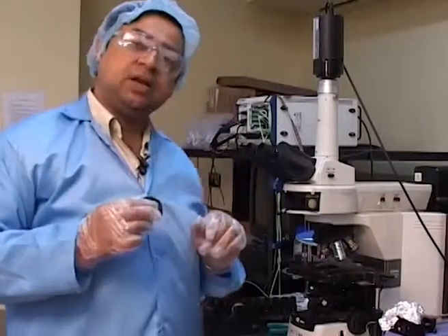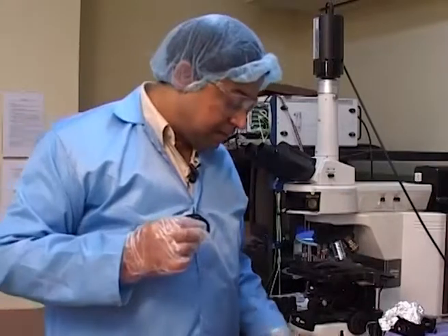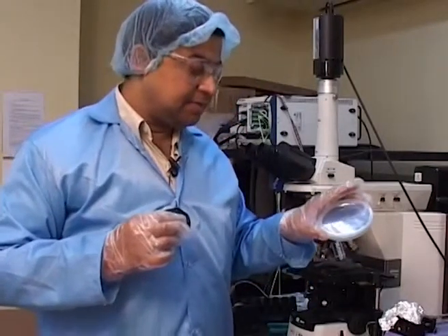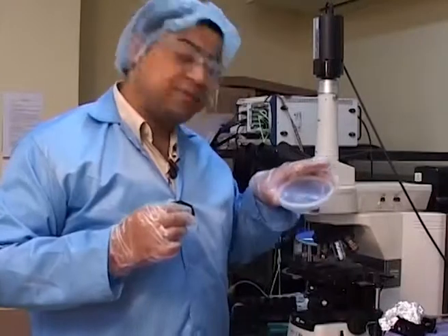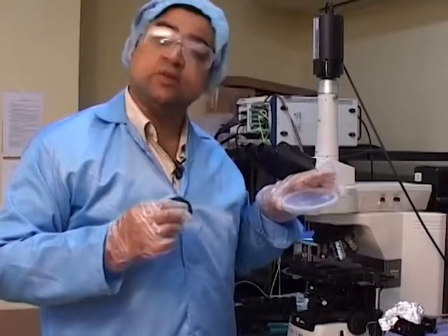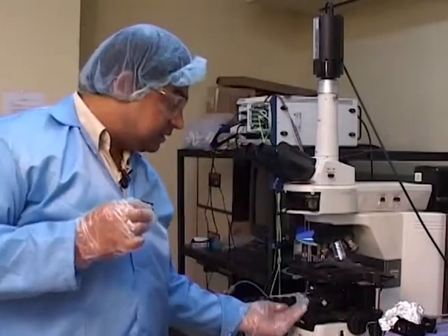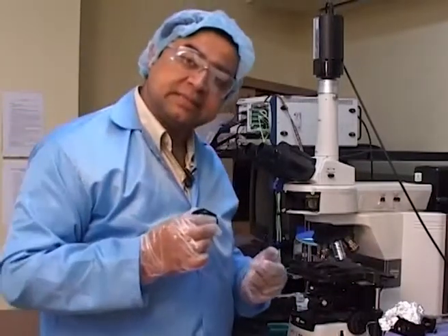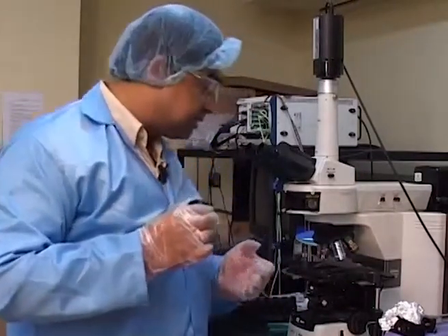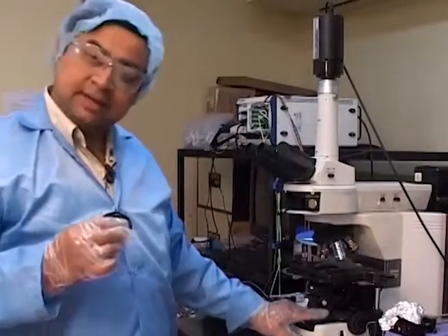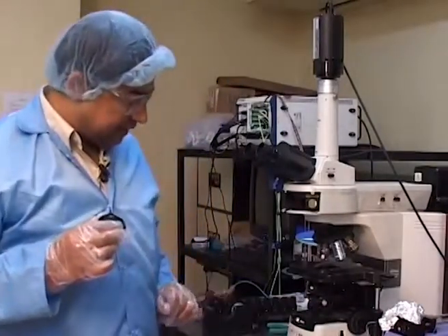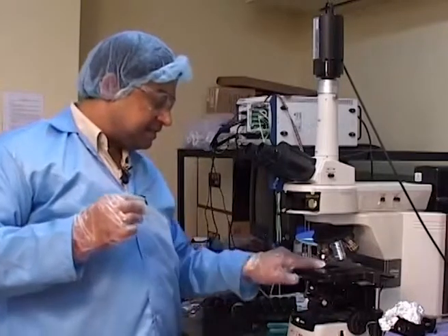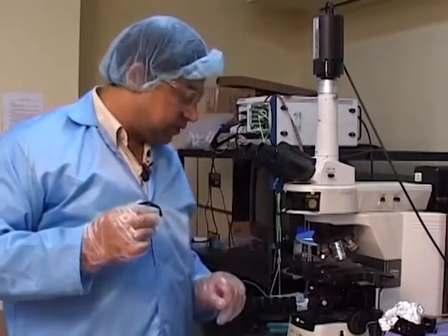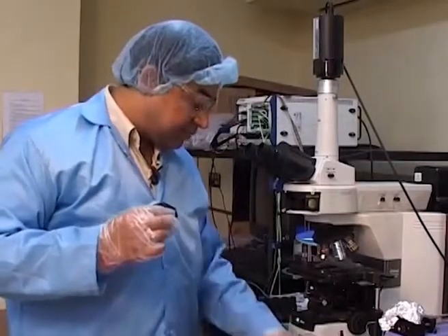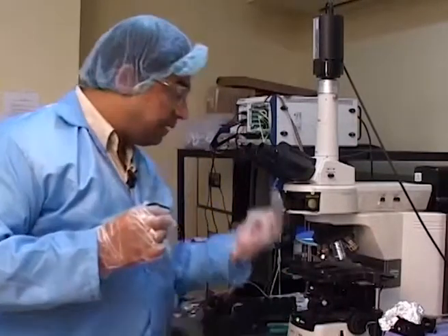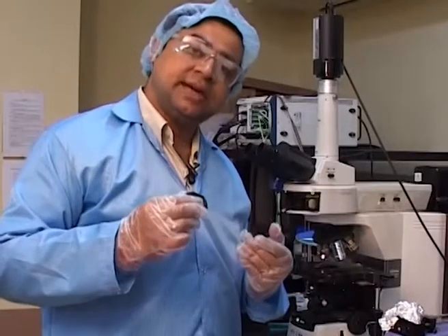Now, in a bright field, dark field option, particularly for lithography, the problem that we face is that we cannot image these silicon wafers, which are actually opaque, using an inverted mechanism of light. In glass samples, glass holders, or transparent or translucent samples, that is still possible. There is a light source here in the microscope, which is actually white light, as you can see, which can go past the sample surface if the sample is kept at this particular stage. However, in our case, if I put the silicon and the silicon is opaque, the light will not be able to go past. So, this is really not the imaging modality we are looking at.